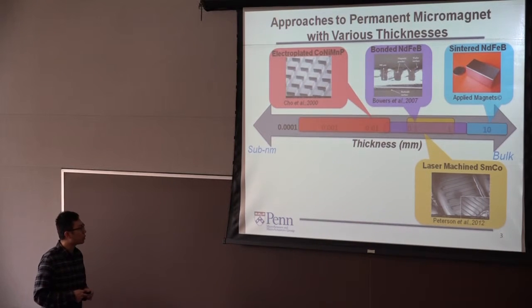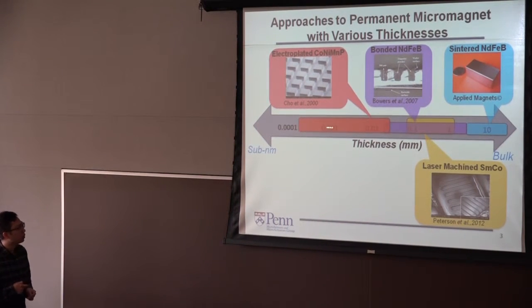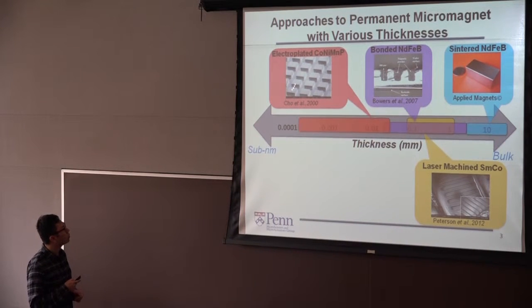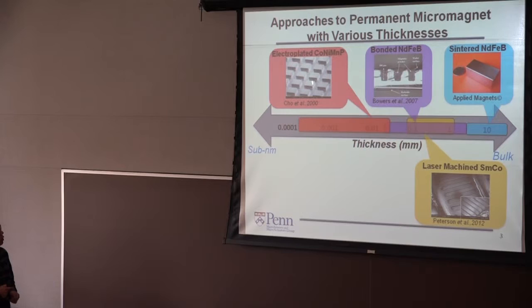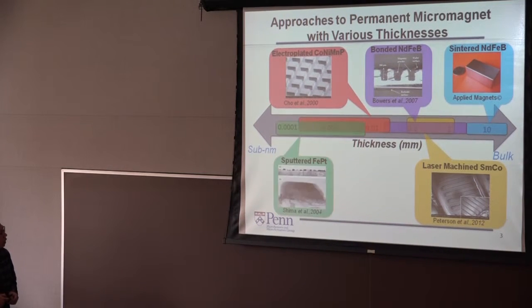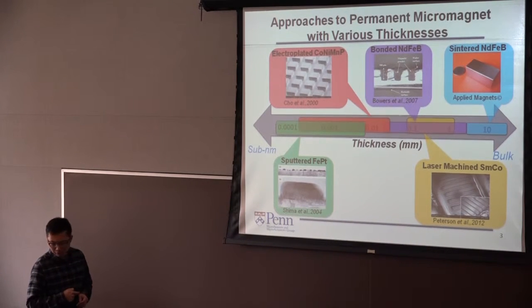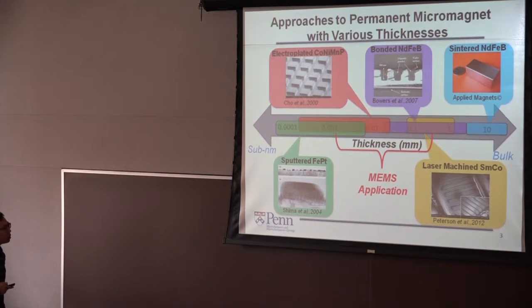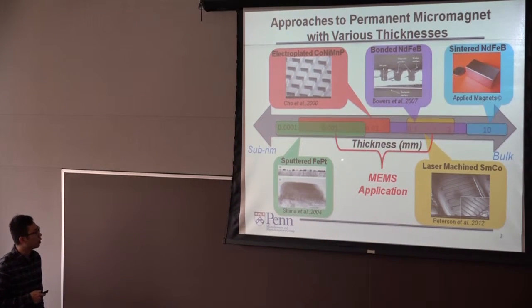So if you want to fabricate a thinner magnet, apparently the length scale is much thinner than over here. You can use electroplating as one of the methods. Here you can see a cobalt nickel manganese phosphorus alloy plated through a mold, the traditional UV-defined photoresist mold. And if you want to plate it thicker, there are some constraints, which I will talk about later. A sputtered magnet is normally even thinner, and the speed is slower. As we mentioned, there is a length scale that is specifically important to MEMS. It's normally 1 micron to hundreds of microns, the perfect permanent magnet length scale for MEMS.